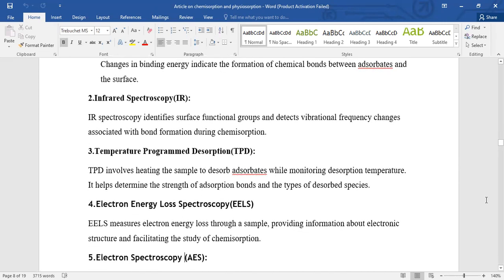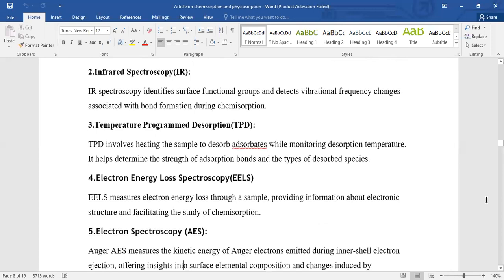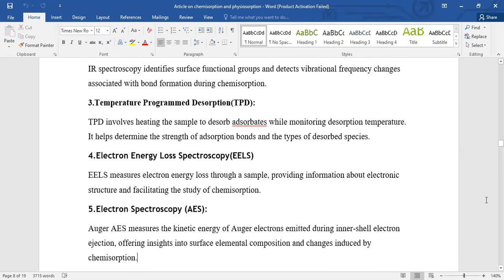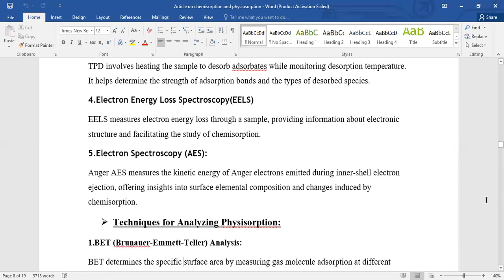Number four is electron energy loss spectroscopy. Electron energy loss spectroscopy passes electrons through a sample, providing information about electronic structure and facilitating the study of chemisorption. And last one is Auger electron spectroscopy. AES measures the kinetic energy of Auger electrons emitted during inner shell electron ejection, offering insight into surface elemental composition and changes induced by chemisorption.